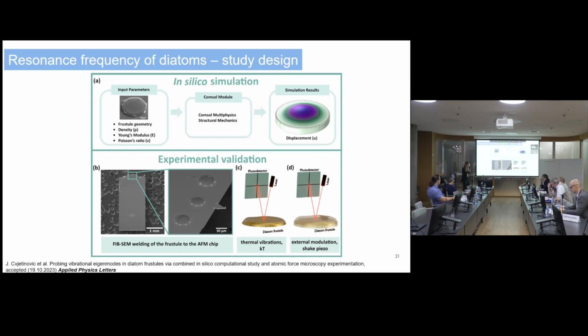And then this whole procedure was followed with sputtering with a thick layer of gold or tin, 30 nanometers, to increase the laser reflectance. So we applied two different methods based on the collection of frequencies of thermal vibrations, as well as by external modulation by exciting the piezo driver.